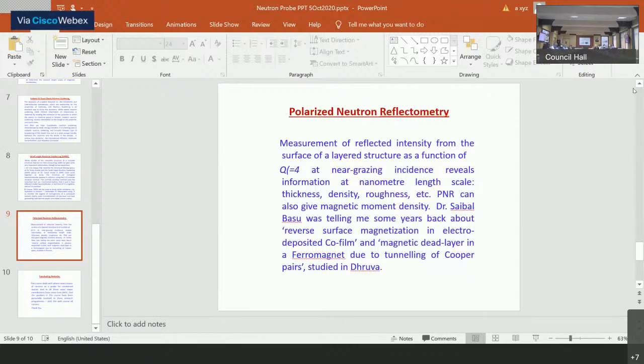This is polarized neutron reflectometry. So you can take a look at grazing incidence, and you can measure the reflected intensity from the surface of a layered structure. Q is equal to 4 pi sine theta by lambda. Of course, this slide got slightly corrupted at near grazing incidence, and you can reveal information at nanometer length scale: thickness, density, roughness, and you can also get magnetic moment density.